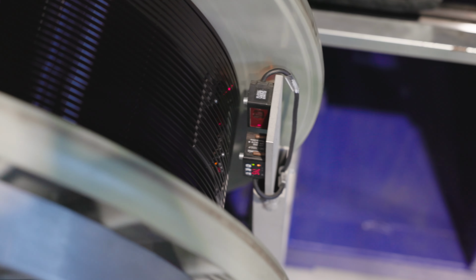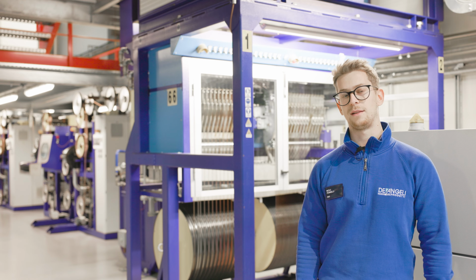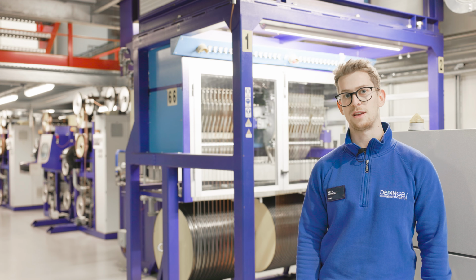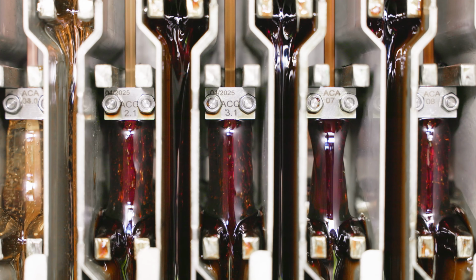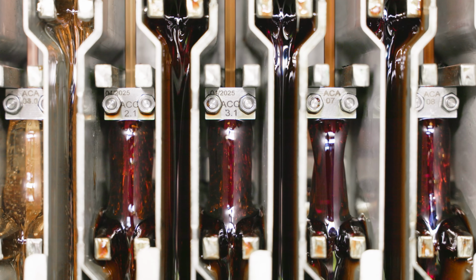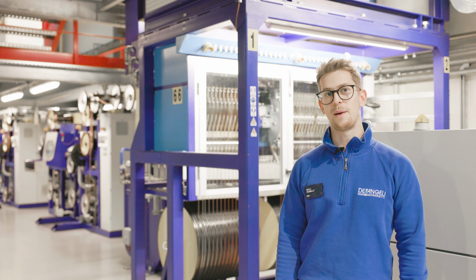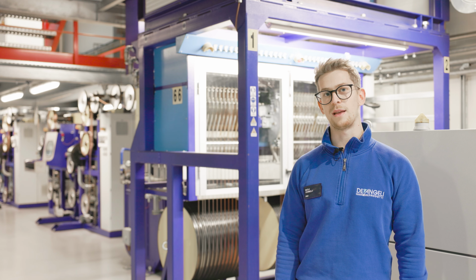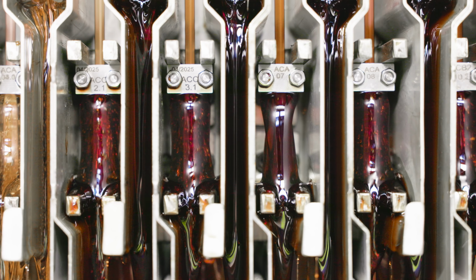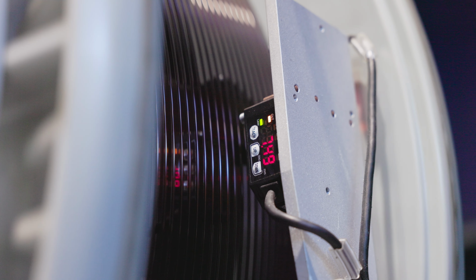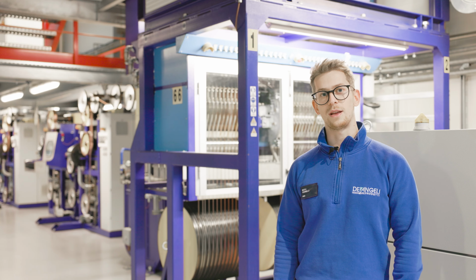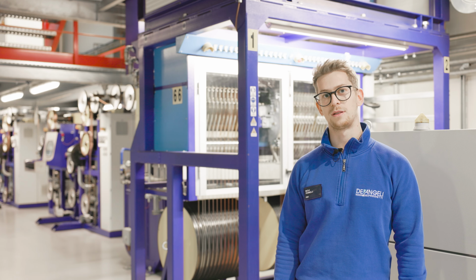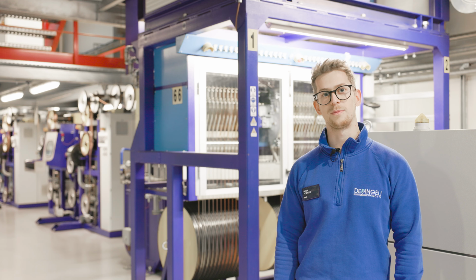A fundamental part is the decision of the enamel with the viscosity and the number of the passages for the line in order to apply the exact quantity of the enamel to avoid possible defects on the surface of the flat wire. The enamel type and the number of passages are a decision that is made together with the R&D department with their study through the viscosity and the tangent delta application. We can also reach up to 150 microns of the varnish per side in order to guarantee the request for our customer for the best e-mobility solution.